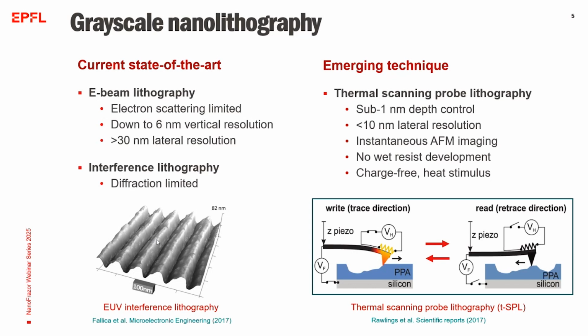by diffraction. In our research group, we mainly focus on thermal scanning probe lithography due to its extraordinary grayscale patterning capabilities. This approach uses a heated nanotip to locally sublimate the polymer surface, and with the same tip, we can write, so remove material, and read what is patterned instantaneously. With this integrated feedback, we can achieve sub-nanometer depth control, allowing us to pattern grayscale structures.